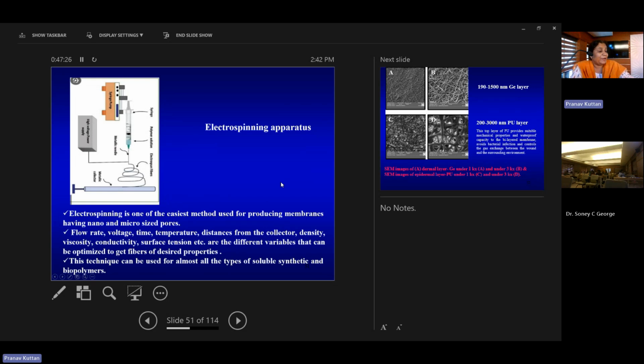So the flow rate, you will be knowing, you will take the polymer and fix it there, and the flow rate can be adjusted, how it will be falling onto that drum. Then the voltage applied, all these things can be looked into in the literature and finalized. Then the time, the temperature, distance from the collector, then the viscosity, surface tension, etc. have to be looked at before finalizing the polymeric solution. Then we can optimize to get fibers of the desired properties. This technique can be used for both synthetic polymers and biopolymers. So here we have used it for polyurethane as well as gelatin.